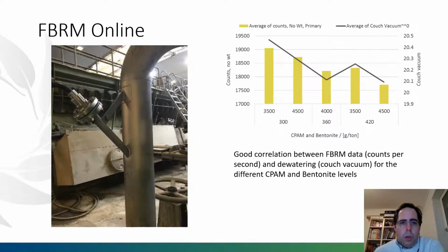We also worked, the same as we have done on the pilot machine with the FBRM, with the possibility to install this online. And what we see now on the screen is a relationship that we had at the mill between the dosage of chemicals, the data from the FBRM, and the couch vacuum, and therefore the dewatering at the end of the wire. And we could see that there was quite a good relationship that allowed us, using the FBRM, to have a continuous optimization.